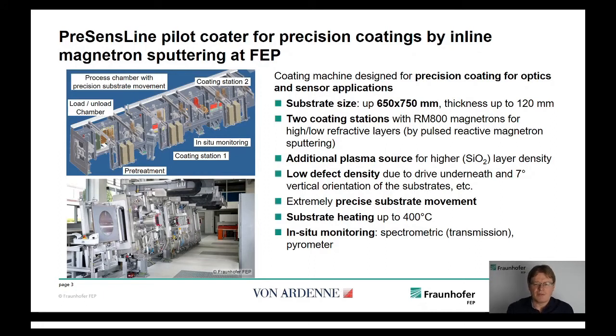We achieve a low defect density. This is, as you see, a vertical inline coater, and the things that are needed to move the substrate are below the substrate. So there are no particles from the movement system. The movement system is very precise. I will say a few words about this later. We can heat up the substrate up to 400 degrees C, and we have an inline monitoring.